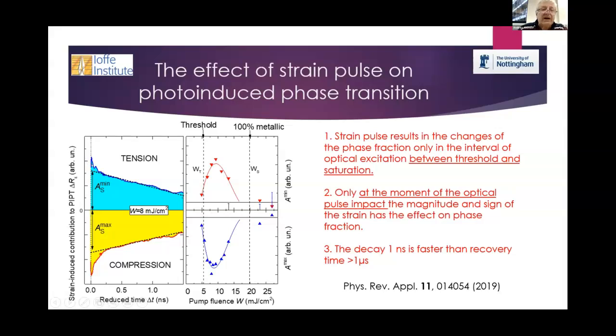So in tension we have increase decaying with about 1 nanosecond. In compression we have decrease. Here we have increase, decrease, and this happens only when we have a pump fluence between the threshold and saturation.